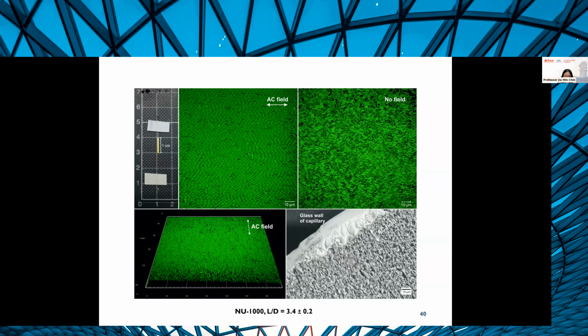And the reason for this is that you have to consider how we achieve this packing. So we used an E field and we induced a dipole in each particle. So if I have positive on the right side and negative on the other side, and I have a neighbor that has the same dipole, they don't want to be next to each other, but rather they want to be staggered and offset. Otherwise, they will end up having electrostatic repulsions. And that explains why we don't end up with a smectic phase.